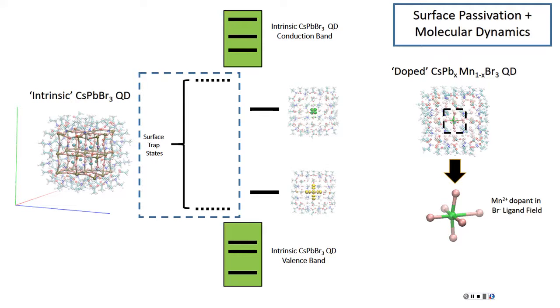But potentially. In your results, when you run dynamics, are your ligands going out? We don't see any pop off. We'll get to that in a second. And then hypothetically, it can pop off. And generally, in an arbitrary quantum dot or surface, you may expect that popping off of a ligand will result in creation of a trapping state. Yes, which is bad because it reduces PL, and that's what these quantum dots are used for. So you recognize the possibility of this adverse effect and are giving us a heads up that this effect should be taken care of. Yes, okay. Just setting the stage for results seen later.